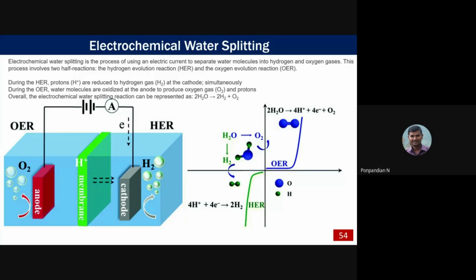And now we wanted to use this material in electrocatalytic splitting of water into hydrogen and oxygen. Here you can see the picture. In the right side picture, you can see how the oxygen evolution reaction takes place. In the first quadrant, generally the oxygen evolution reaction, and in the third quadrant you can see the hydrogen evolution reaction taking place. In this graph, this is an electrode, and this happens in a full cell setup. On one side there is the oxygen evolution reaction at the anode, and at the cathode the hydrogen evolution reaction happens.